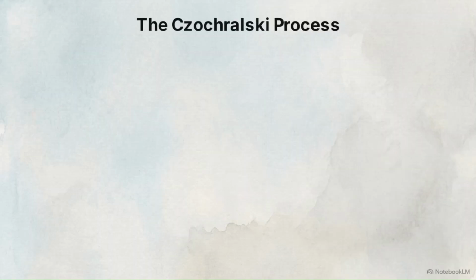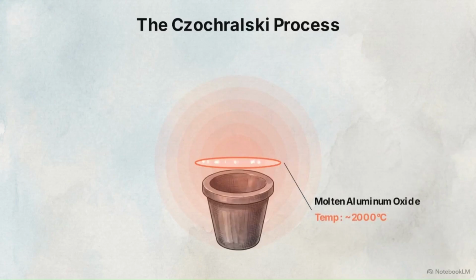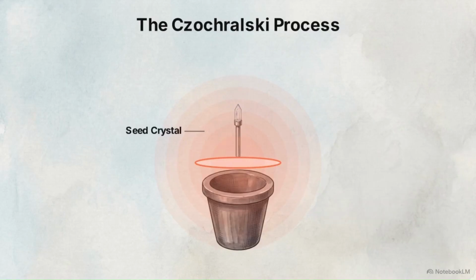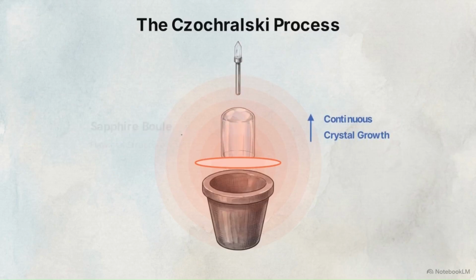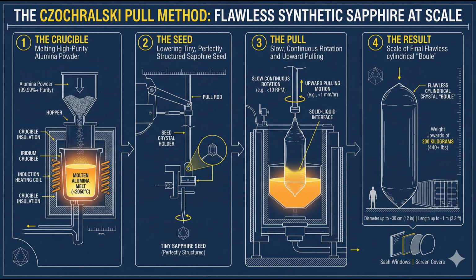Because the molten alumina naturally wants to align with the existing crystalline structure of that seed. Exactly right. As you slowly pull the rod upward while continuously rotating it, the molten material cools and crystallizes onto the seed. So you're literally pulling a giant crystal out of a molten bath. By painstakingly controlling the temperature and the pulling speed, you can grow massive, flawless, cylindrical boules of sapphire. We're talking crystals that weigh over 200 kilograms.